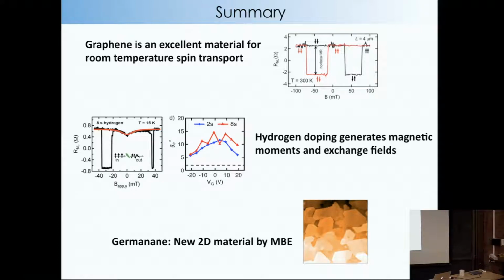With this new material, do you expect an opening of a gap because of spin-orbit coupling? Yes. If we got the version that didn't have hydrogen or was only slightly buckled, that's a Dirac material, and the gap is predicted to be about, I think, 50 meV, which is a good size gap for quantum spin Hall effect and things like that. The most exciting prediction for this class of materials is the one with tin. Xiaocheng Zhang has a preprint up, and you're able to get a spin-orbit gap of about 300 meV, and a regular gap of about 300 meV also. By changing the functionalization, what terminal groups you put on there, you can convert it from a regular insulator into a topological insulator. So it's controlled by the chemical bond. That is super exciting. So anyways, we're going to try that.